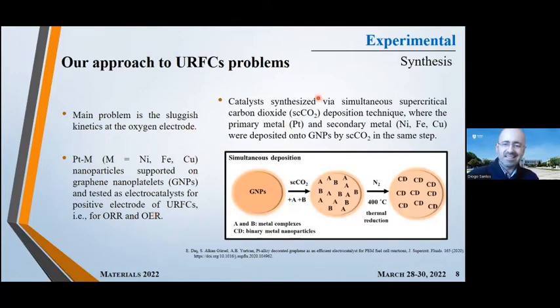So these catalysts were prepared by a simple process known as simultaneous supercritical carbon dioxide deposition technique, where the primary metal, the platinum, and the secondary metal were deposited on the graphene nanoplatelets by this simultaneous supercritical CO2 deposition, in the same step. So here we have a scheme on how the process goes.